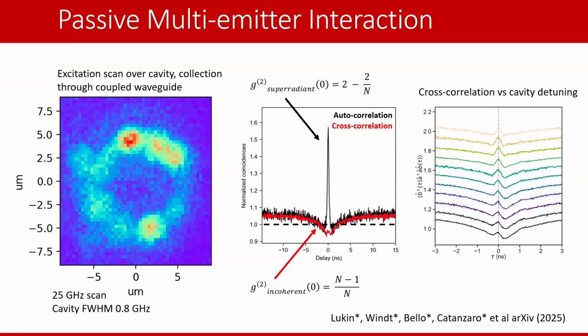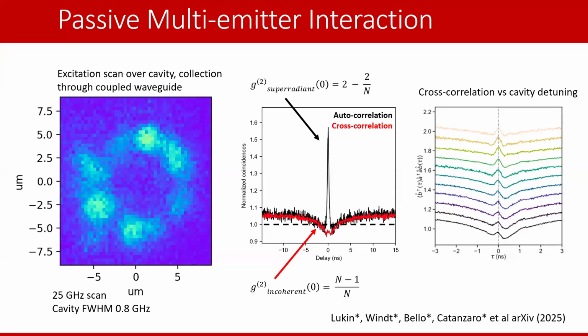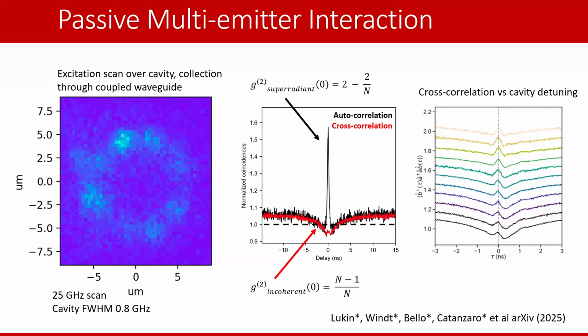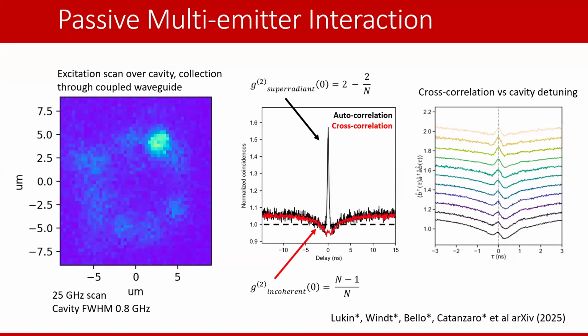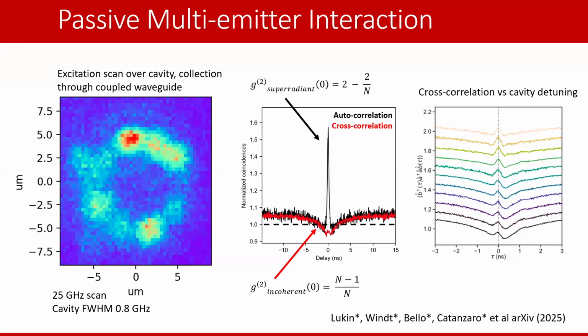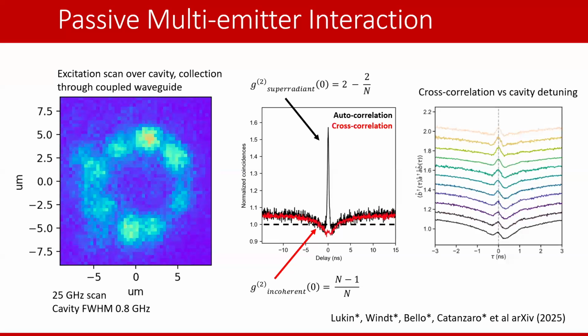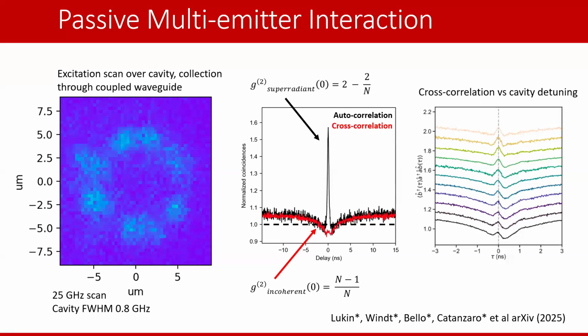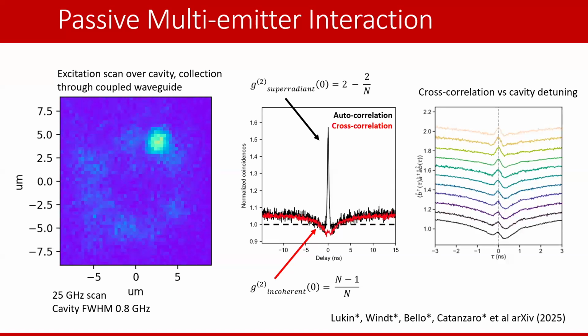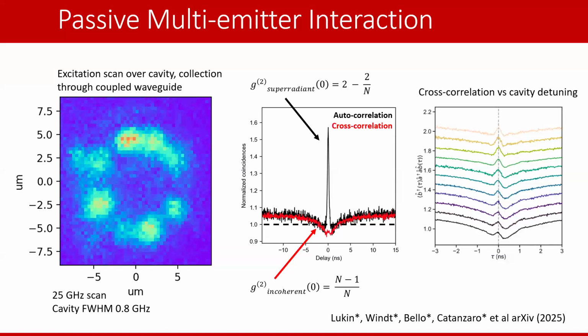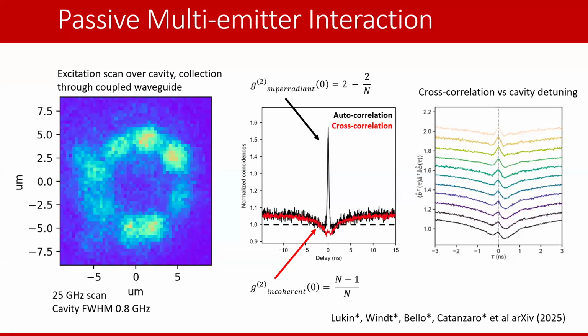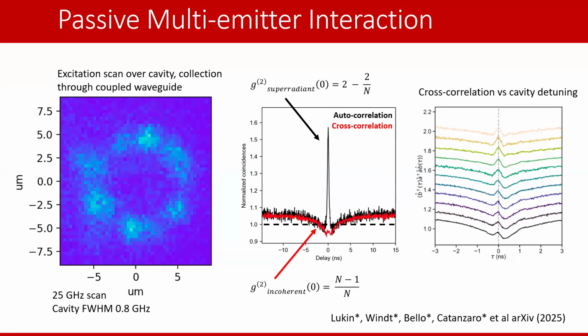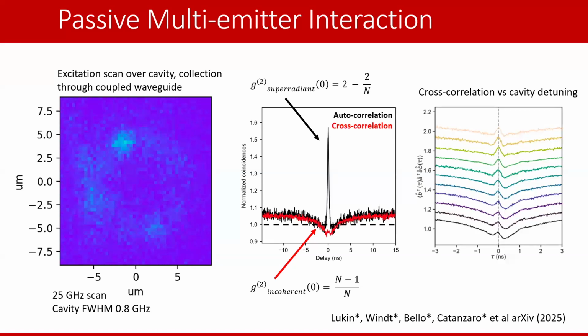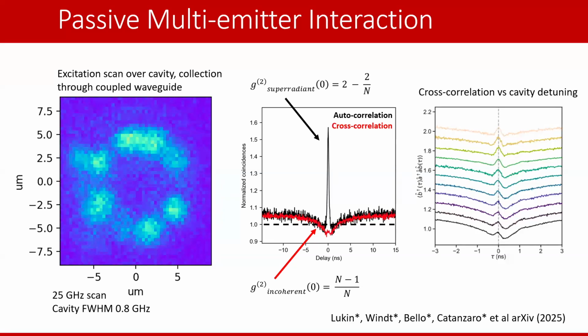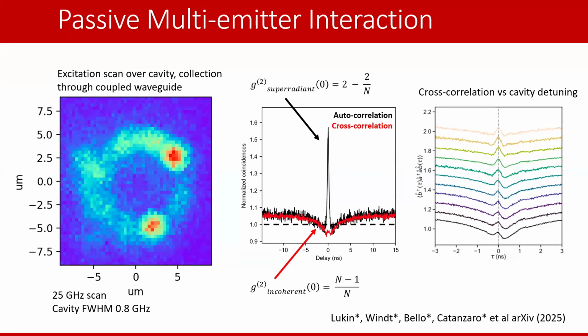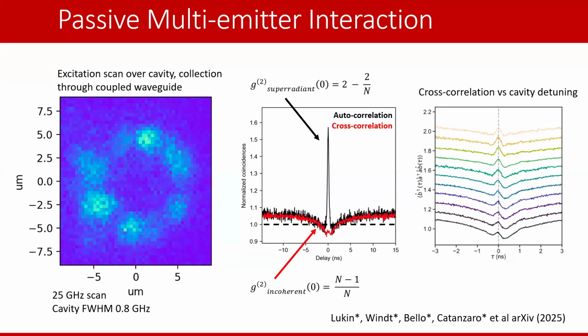We see this interesting emergent chirality from the photon emission. Because of the way the phases tend to add up as you emit photons, the system will emit a photon first to the clockwise and then to the counterclockwise. And so you can see these correlations, and this is interesting. This is evidence that there is correlated behavior in the system because all of the defects are individually strongly coupled to the cavity mode. But there's not so much you can do with this other than say, okay, this is evidence that something interesting is going on, but we can't really control it. We can't do gates. We can't do spin-photon entanglement because fundamentally, because the defects are moving around so much, we just have many two-level systems randomly coupled at random times.